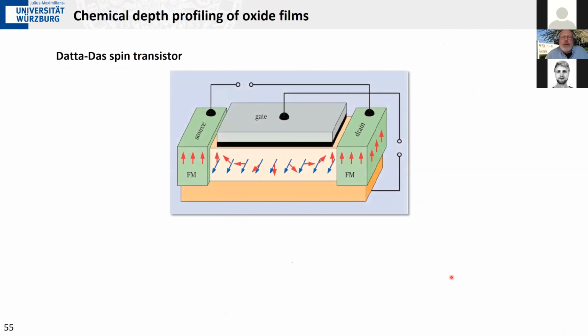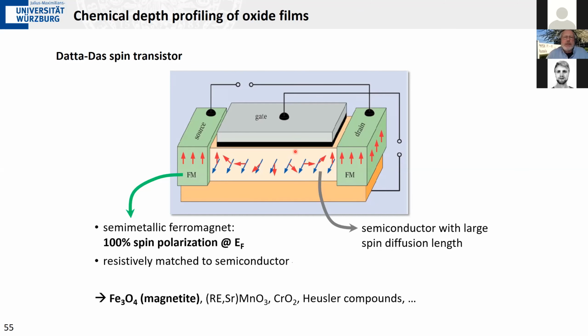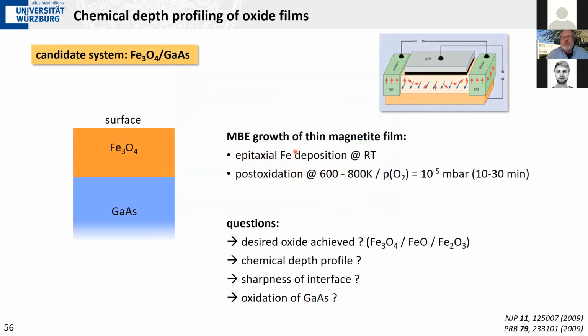You can also do depth profiling once you have enough depth information, and here I will motivate this with this example of a spin transistor, which depends on ferromagnetic electrodes. And here you have a transfer channel, which typically would be a semiconducting material. So you need a semiconductor, and you need a ferromagnetic electrode, which has to deliver a current of 100% spin polarization. So you ideally want to have a semi-metallic ferromagnet, and magnetite is a candidate compound for this, and then you put this onto some semiconductor, and then you hope you get a nice interface.